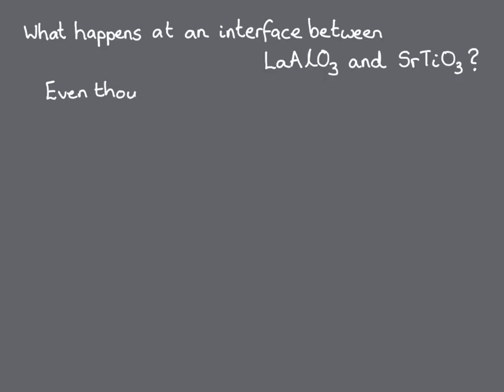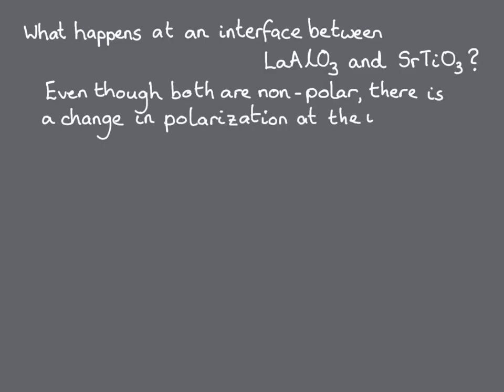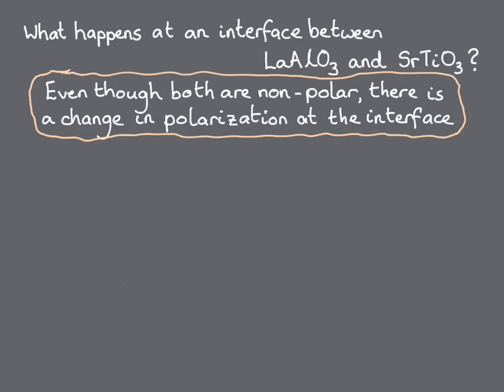So what happens at the interface between lanthanum aluminate and strontium titanate? Well, even though both materials are non-polar, there is a change in polarization at the interface. We call this change a polar discontinuity, and its size, in this case, is half of the polarization quantum.